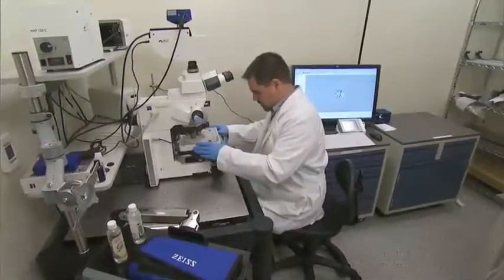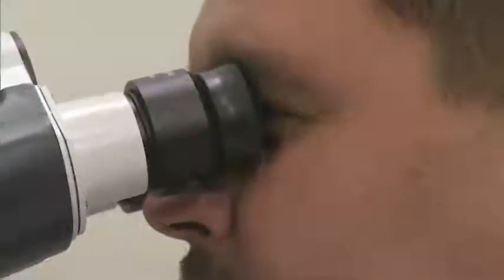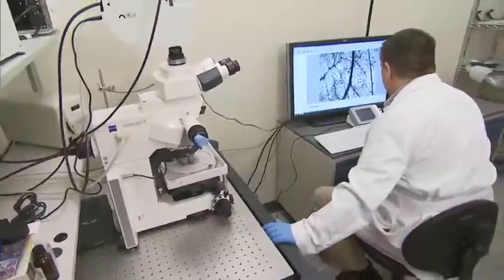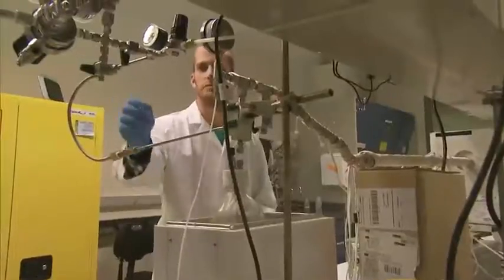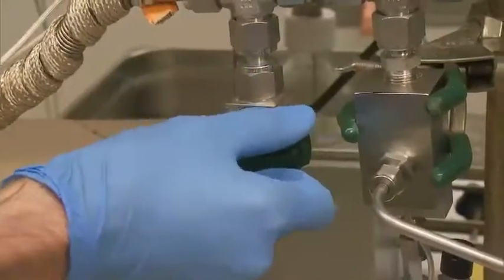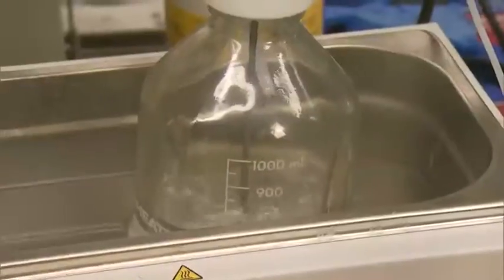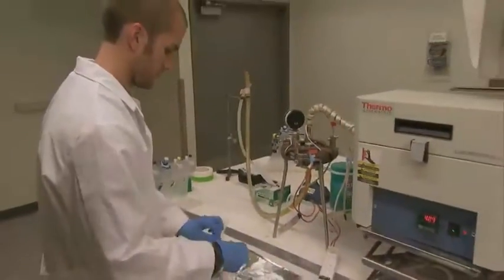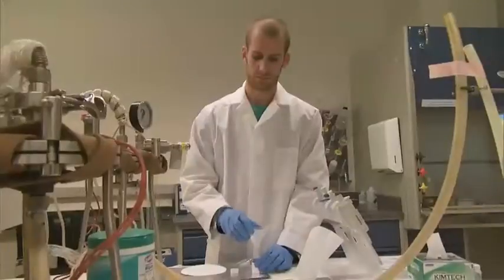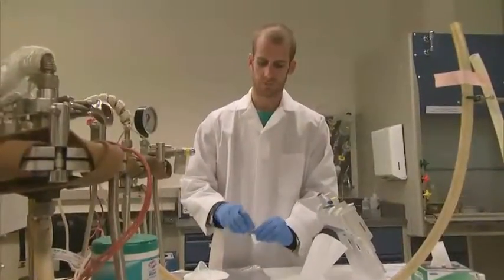There must be some challenges with the types of equipment that you have to use to even study this. There are two aspects of this. One, the equipment that we need to look at these particles is very expensive because we have to use what's called electron microscopy. But I can make these particles with very simple techniques. The one major way that we make these nano sponges, if you will, is something like a vaporizer, right? You plug it in and it creates little liquid droplets. So what we do is make liquid droplets, and within those droplets we put particular chemicals that, when the droplet evaporates, are essentially pre-programmed to form this nanostructured material. So it's simple. It's called self-assembly.